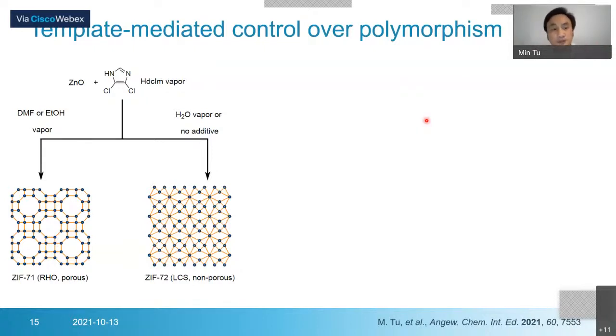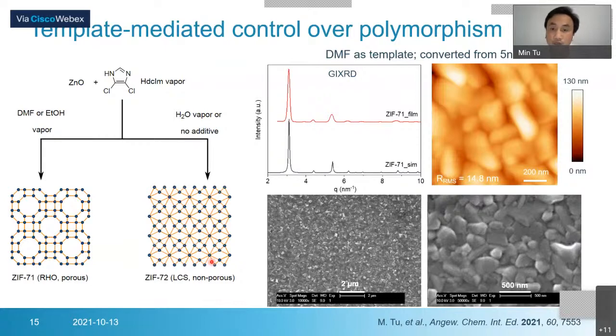So during this chemical vapor deposition, we have zinc oxide reacted with dichloroimidazole vapor, and we introduce, for instance, DMF or ethanol vapor, we get this porous structure. But when we introduce water vapor or we didn't add any additive, we get this ZIF72, this dense phase. So here I just show you one example.